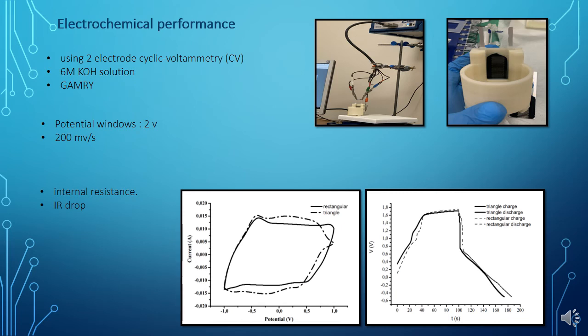Our experimental setup consists of a system that we designed and manufactured with a 3D printer to hold our specimen during the experiment, and the electrochemical performance of the electrodes was analyzed by using two-electrode cyclic voltammetry in 6 molar KOH solution. CV curves of electrodes with rectangular and triangular shapes are shown in the pictures. The electrodes were analyzed at 200 millivolts per second scan rate, between 1 and -1 potential range, under the same conditions.